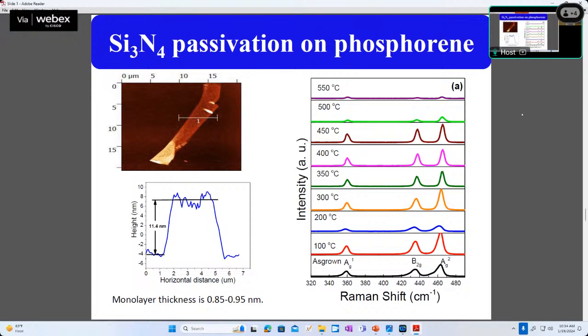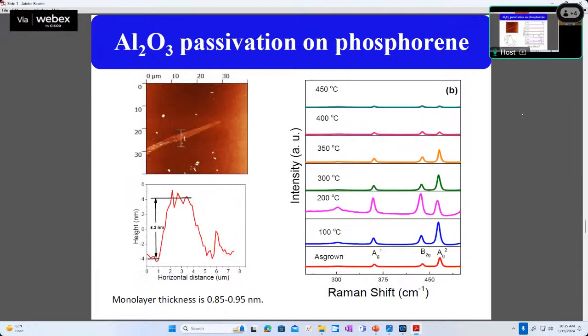This material becomes very stable up to 550 degrees centigrade. So any high temperature device you can also fabricate using this material. You can see here all the Raman peaks are present up to 550 degrees centigrade. This was the beauty of this passivation technique. About the thickness of this material, another technique called atomic force microscopy was used here. Similarly, aluminum oxide passivation was also used to stabilize this material, and up to 450 we got Raman peaks.